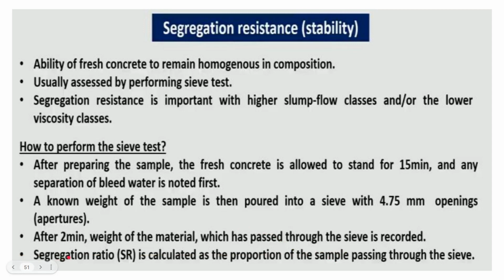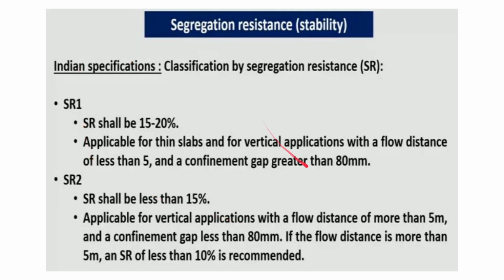From that we find the segregation ratio, SR, which is calculated as a proportion of the sample passing through the sieve. That is, the weight of material passing through the 4.75 mm sieve divided by the actual weight of the sample poured into the sieve. The segregation ratio is also classified into two ranges, SR1 and SR2, as per the Indian specification IS 1199 part 6.